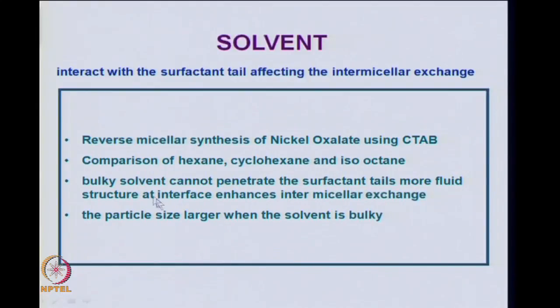Now, if you have a bulky solvent, it cannot penetrate the surfactant tails at the interface. At the interface of water and oil, that is water and the non-aqueous medium, the surfactant will be aggregated, and the bulky solvent, which is outside this interface, cannot penetrate the surfactant tails, and hence the interface becomes more fluid. And whenever the interface becomes more fluid, that enhances intermicellar exchange. In other words, whenever you have bulky solvent molecules, you have more fluidity at the interface and you have enhanced intermicellar exchange. And when you have enhanced intermicellar exchange, the particle size will be larger, and hence particle size is larger when the solvent is bulky.